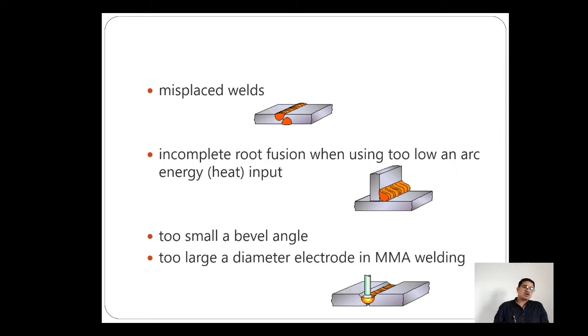So friends, if you remember, during the qualification of the welding plate, we always need to take a higher heat input in the root welding. The reason behind it is that the root welding needs to melt the root face and also fill the root gap. So if we are not taking the proper or higher heat input, then the welding electrode may not properly penetrate the plates.